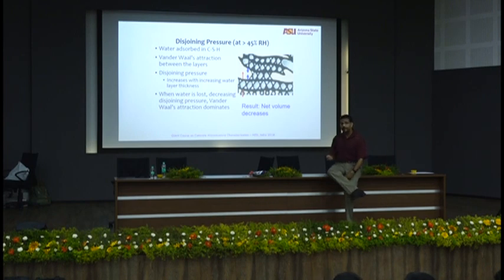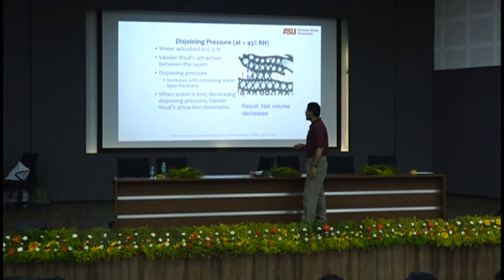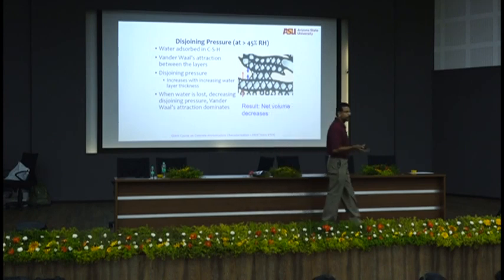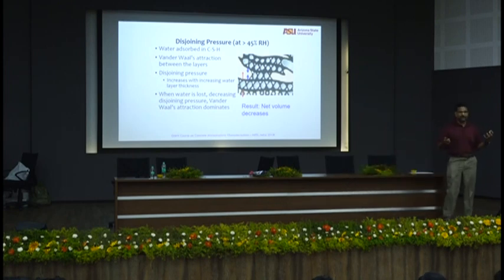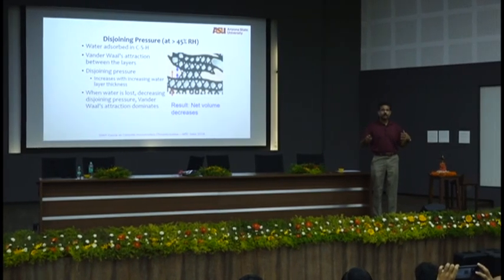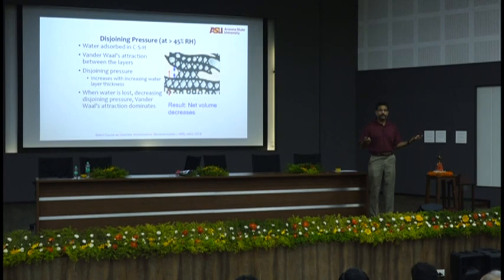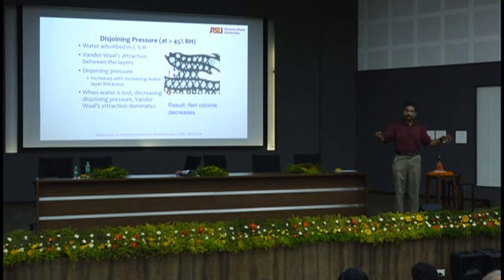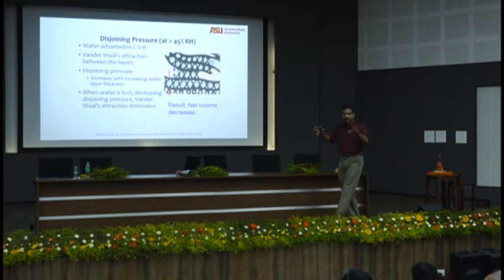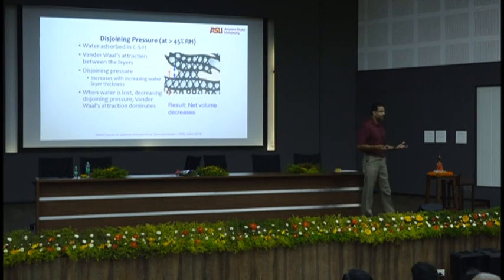The next one, disjoining pressure, also happens at greater than 45% RH, but disjoining pressure is a readjustment. I told you that because of water going out of capillaries, you will have some local readjustment, right? Water goes out of capillaries at what RH? Greater than 45. But when that happens, at that same RH greater than 45, there is some internal readjustment. That internal readjustment is the disjoining pressure, because of the adsorbed water, because of van der Waals attraction between the layers, you start to lose the adsorbed water, resulting in a net volume decrease. So then you have van der Waals attraction dominating between those two layers, because this adsorbed water is gone, readjusting because the environment around that gel is now drier. Okay? So that's disjoining pressure.